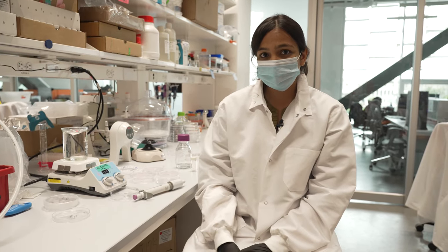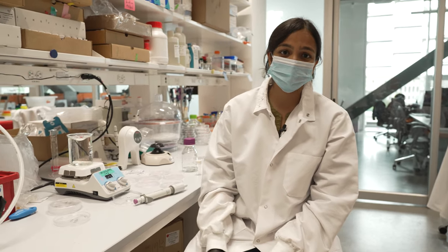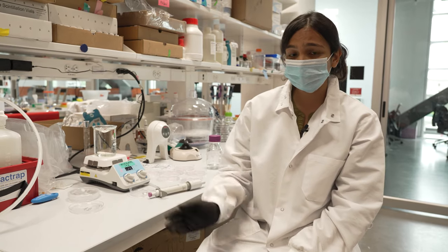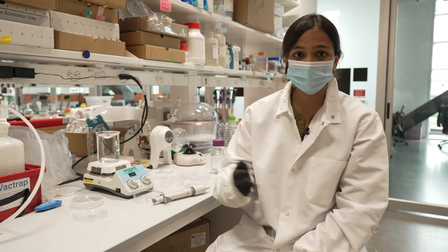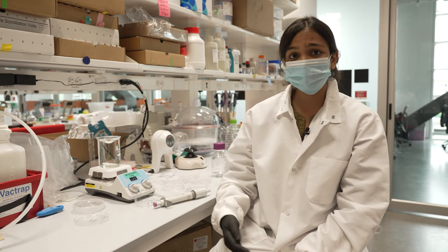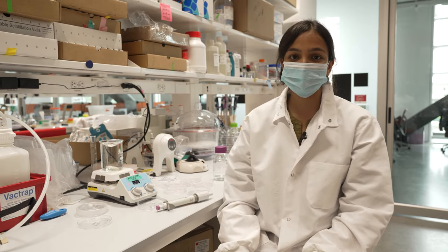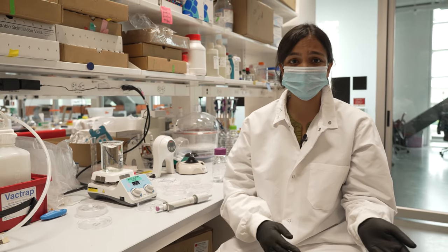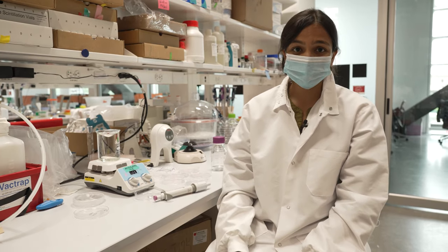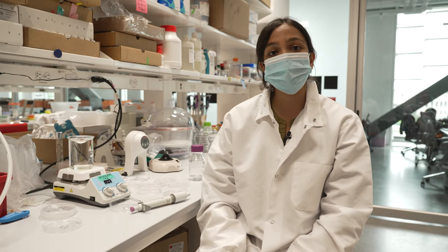The fabrication of these backpacks is a multi-step process. We make PDMS, which are polymeric molds — we make those templates. We spin coat, which is basically just spreading different layers of polymers, drugs, and antibodies onto them. Then we print them, which is basically transferring from the PDMS layer to a petri dish where we can collect the backpacks. We then concentrate them and bind them to macrophages.